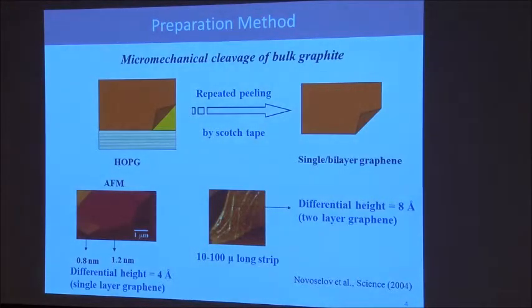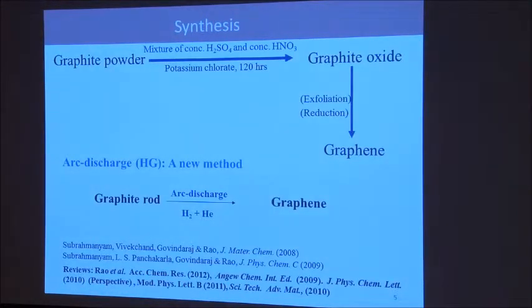But normally most people don't prepare graphene this way; they use chemistry. Most people take graphite, oxidize it, exfoliate graphite oxide to get single layer graphene oxide, then reduce it to get some sort of graphene. It is actually reduced graphene oxide. You can make single layers of that in solution.